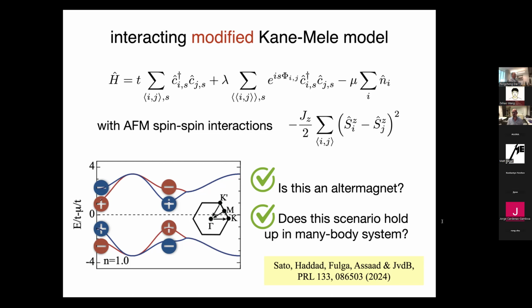Okay. But in the case of manganese telluride, there are actually experiments suggesting that you can tune the spin direction from in-plane to the c-axis by lithium doping, done at Oak Ridge National Laboratory. So would you then expect that there's going to be no anomalous Hall effect in the lithium-doped sample? It might be, yeah. Okay.